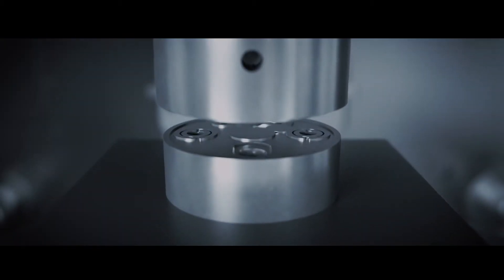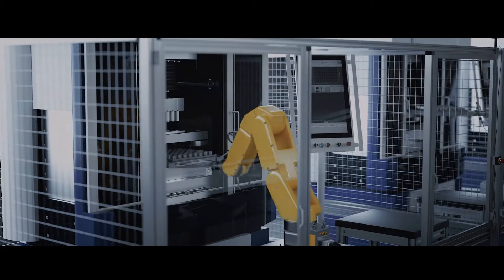The electrode shape is projected inversely onto the metal — contact-free and without thermal or mechanical influences. Workpieces with an imaging accuracy in the lower micrometer range and a surface quality of up to 0.03 micrometers are produced in high repeatability. The entire production technology is thoroughly tested and the quality management certified. It is therefore no coincidence that machines produced by PEMTECH are used in the series production of established manufacturers in many different sectors worldwide.